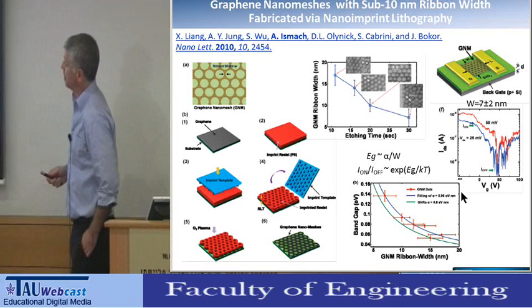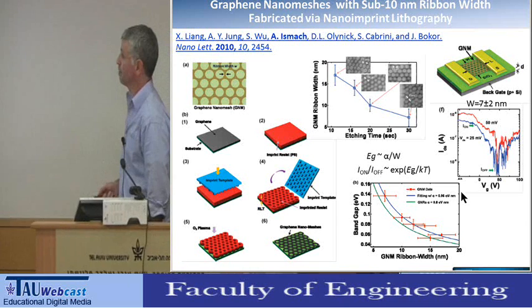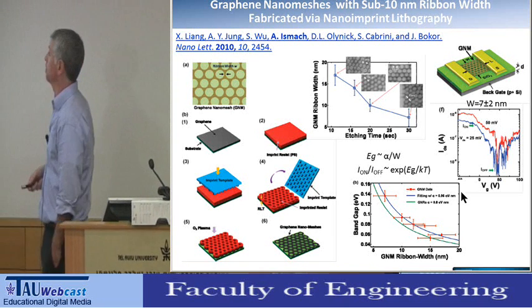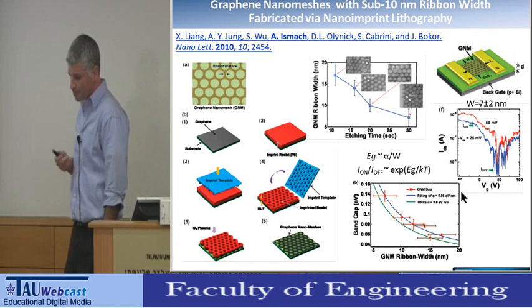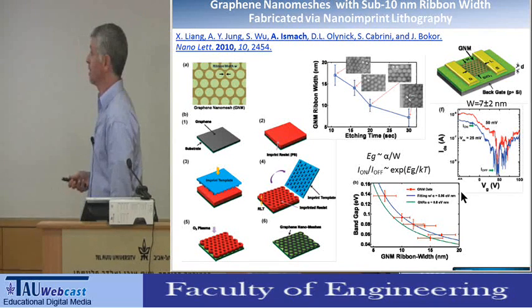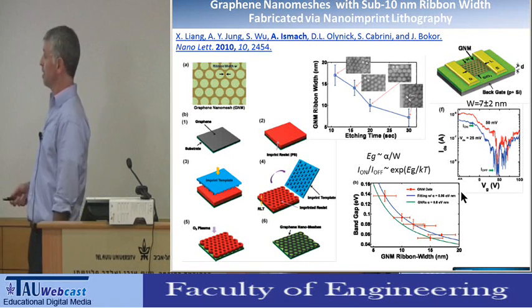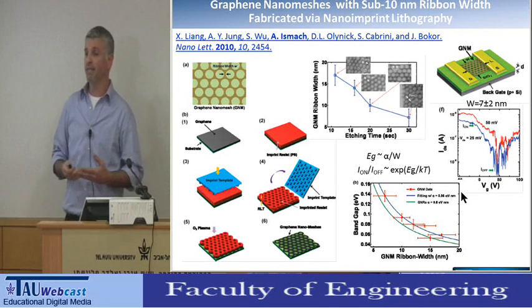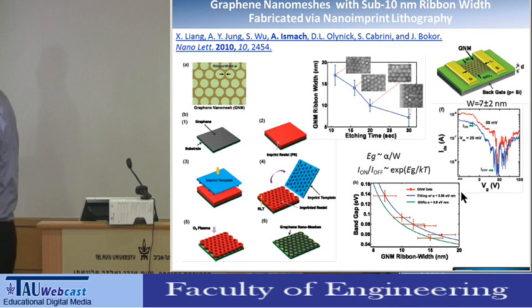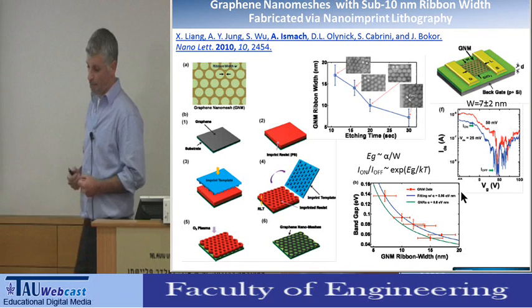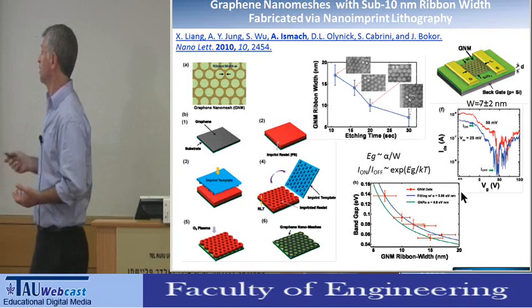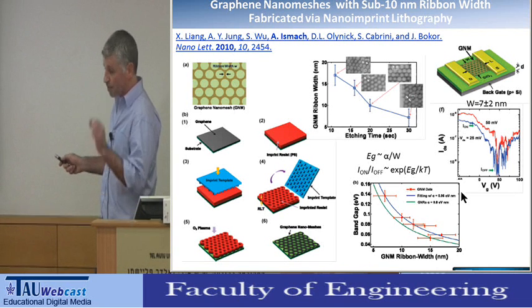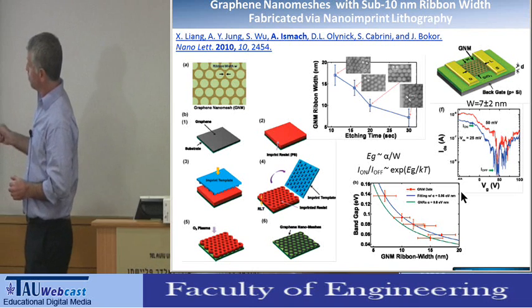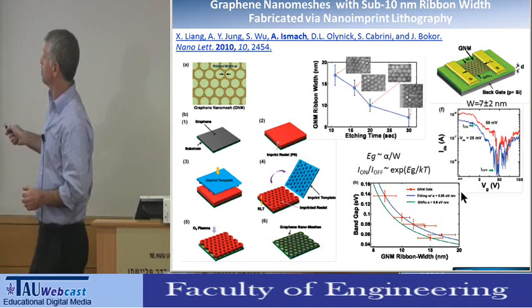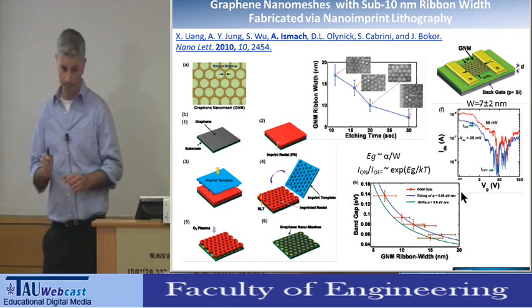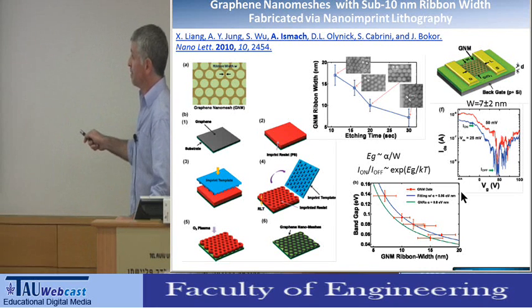I was also involved in developing a way to make large-scale nanoribbons. One of the problems with graphene, and I discussed that with Yossi Rosenbach before, is that graphene does not have a band gap, so it cannot be used easily in applications like microelectronics and logic applications. So one way to introduce a band gap in graphene is by quantum confinement. In this method, we used a block copolymer to make a template for nano-imprint lithography with very small holes. Then, by controlling the fabrication parameters, we could fabricate a series of nanoribbons with different widths.